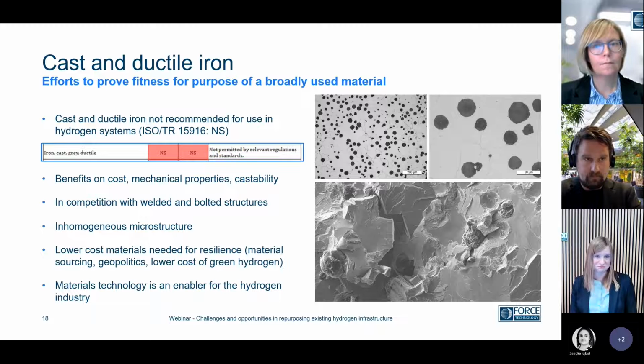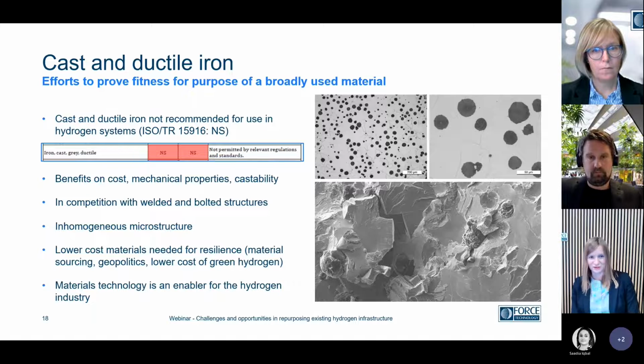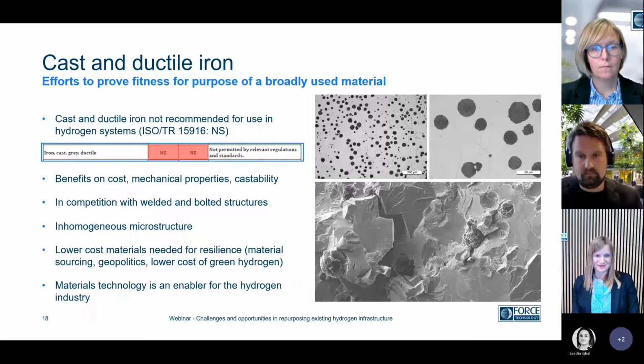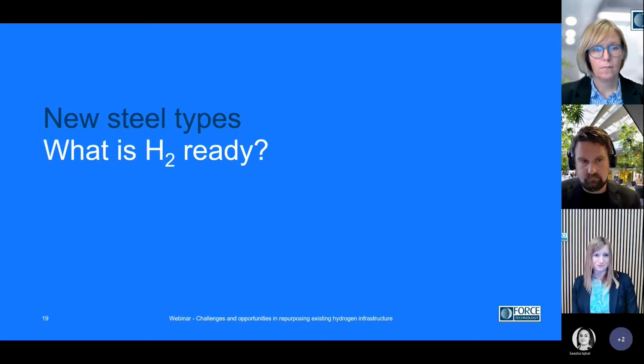So this could possibly be an option because we also need to look at lower cost materials for resilience, a broader material sourcing. We know the geopolitical situation, and just in general to lower the cost of green hydrogen. But as you can see to the right, ductile cast iron consists of a quite inhomogeneous microstructure. We have these dark spots, which is the graphite nodules. And this is a scanning electron microscope image of a brittle fracture in this material. So of course, everything needs to be well tested in order for us to ensure a safe hydrogen service.